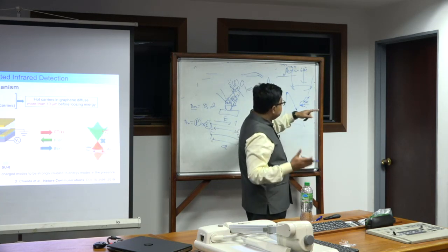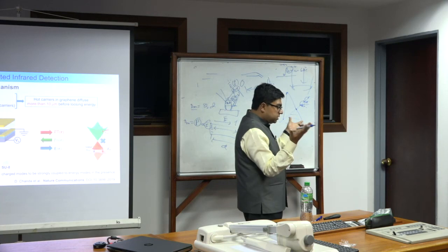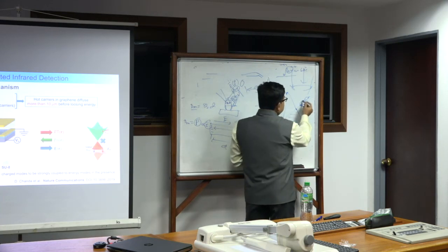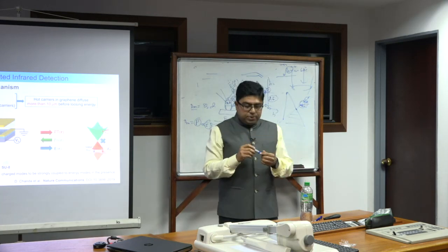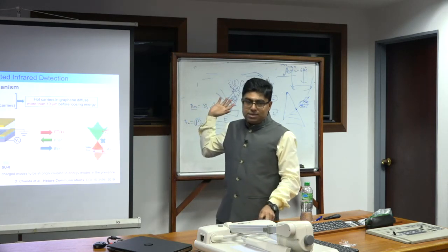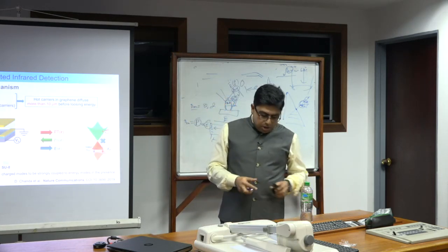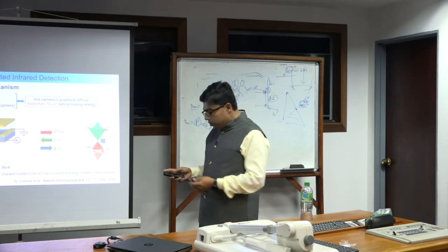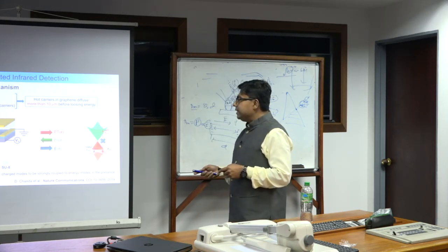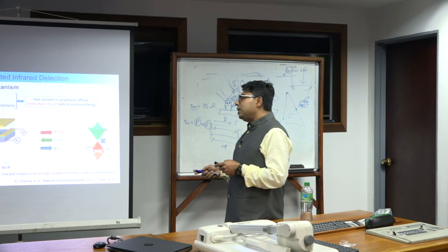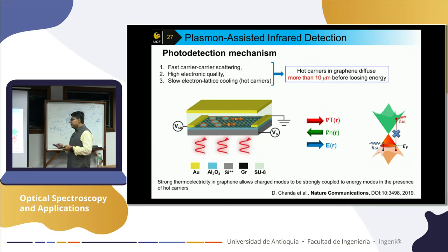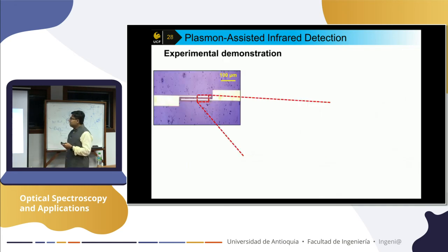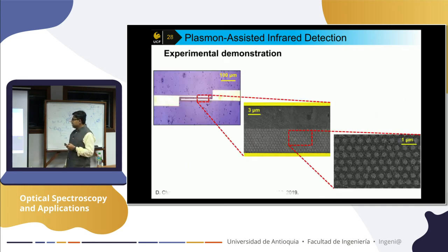The velocity between the train and you gets smaller and smaller. Velocity, in our case, is energy. So they get recombined, and I cannot use graphene for a normal photodetection scheme. So I had to create some clever, different way. We found a technique where we absorb strongly at one end and absorb almost nothing at the other end. Each time you do so, you create a thermoelectric voltage across the graphene, and that's what you measure. So photon in, voltage out. That's your photodetection.